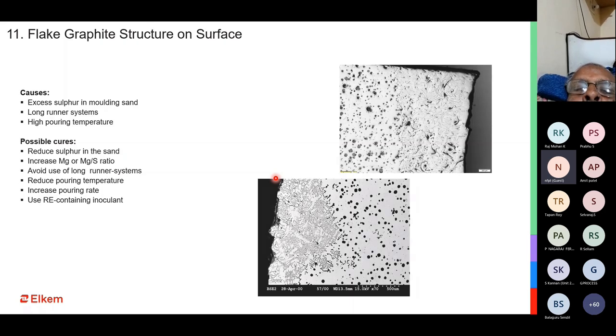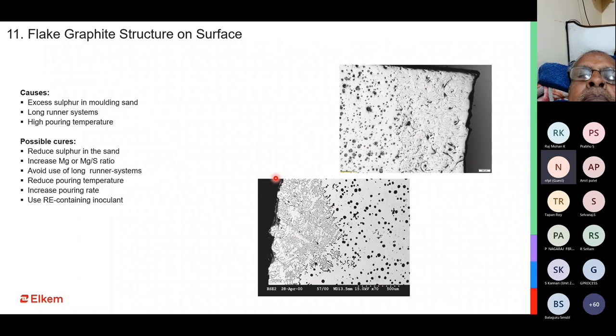How do you control it? You control it by making sure that your sulfur content in the sand is within control, by increasing the magnesium percentage, which means increasing the addition rate of ferrosilicon magnesium, by controlling the temperature and the time that we take for metal tapping, pouring, and the transfers. And lastly, by using a rare earth containing inoculant. This is something we have seen in the past: when we get a surface flake kind of defect in ductile iron, we generally use a cerium based inoculant, which helps control this flake reversal and does not allow the graphite flakes to form on the surface of the casting.